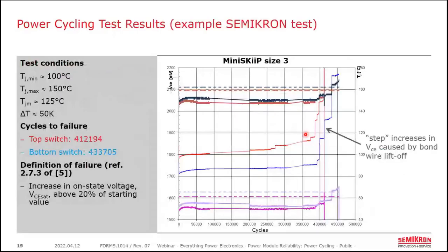Now, the actual power cycling test is pretty simple because we are just heating and cooling the device until it fails. Shown here is exactly that test result for a MiniSKiiP module where an IGBT chip is starting at 100 degrees Celsius minimum. It's being heated up to 150 degrees C, and then cooled back down to 100 degrees C. This gives us a delta T of 50 Kelvin and a mean junction temperature of 125 degrees Celsius.